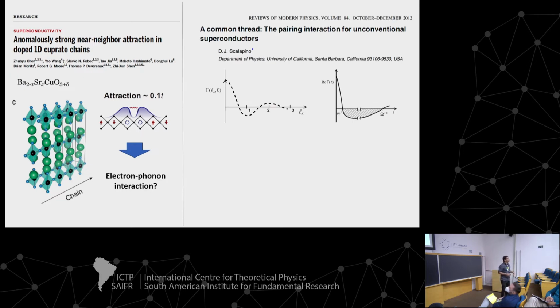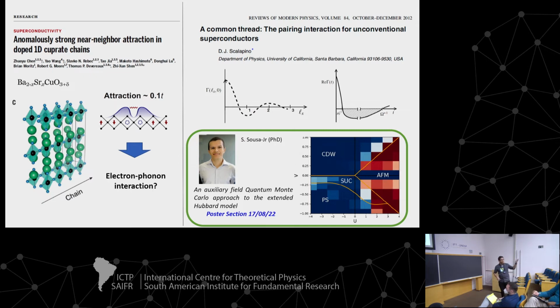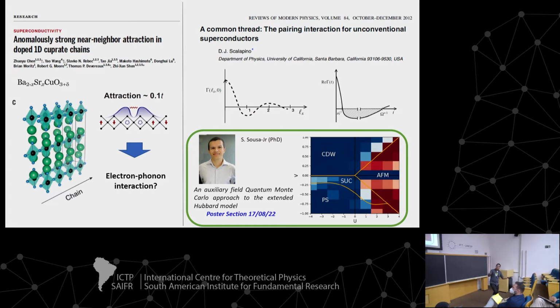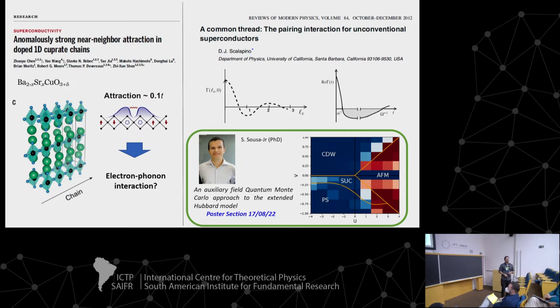And this is one of the ideas of Doug Scalapino in this review, in which he mentions that the electron-electron interaction in cuprates should have attractive interactions for nearest neighbors. And also he explained this by adding phonons. So the phonon energies can give this to you. If you want to discuss a little bit more about this, we also have one student that is presenting a poster here that will present some results on the extended Hubbard model that can, in principle, explain some of these features.